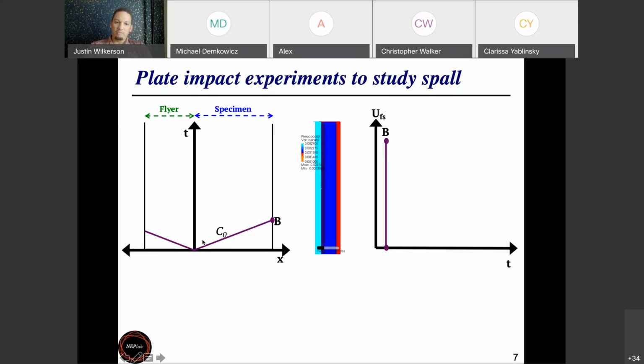When that shock wave hits the free surface, it causes a jump in what we call the free surface velocity. So what we can do is sit back here on the back face of the target material and measure the velocity through the Doppler effect. We hit this with some kind of laser, measure the red shift or the blue shift in the laser, and then through the Doppler effect, you can determine the velocity of this free surface. If we sit and watch what happens to the back free surface, it's moving with zero velocity, zero velocity, zero velocity, and then the shock wave hits, and all of a sudden it accelerates away. It accelerates to the right.